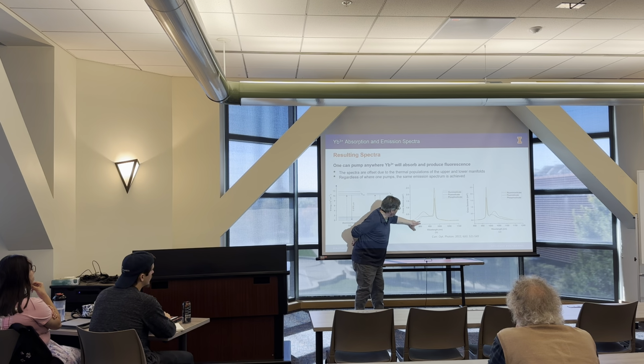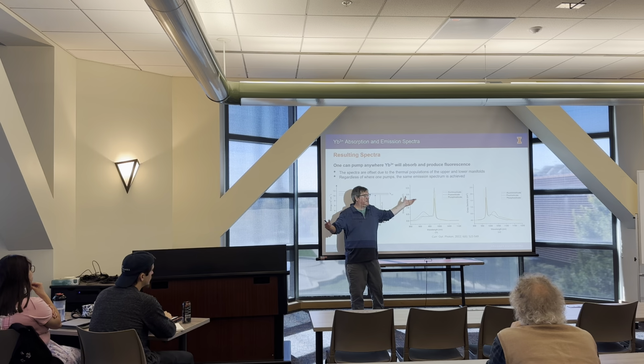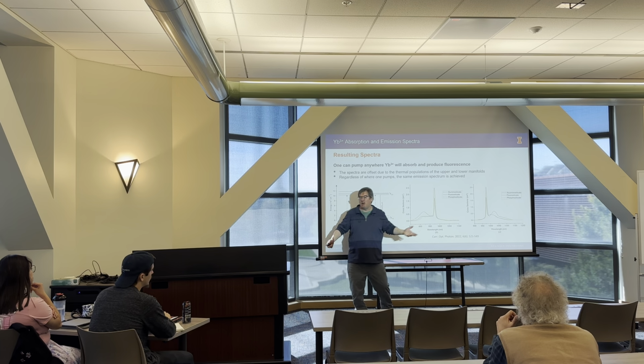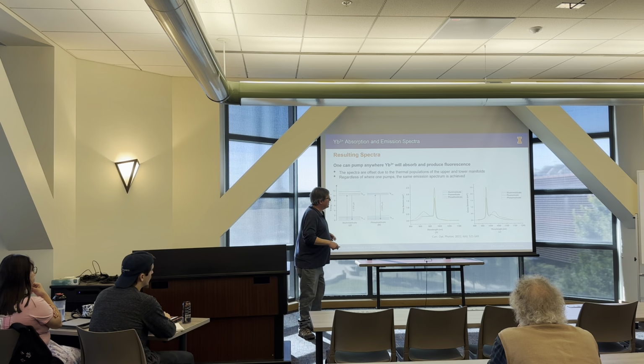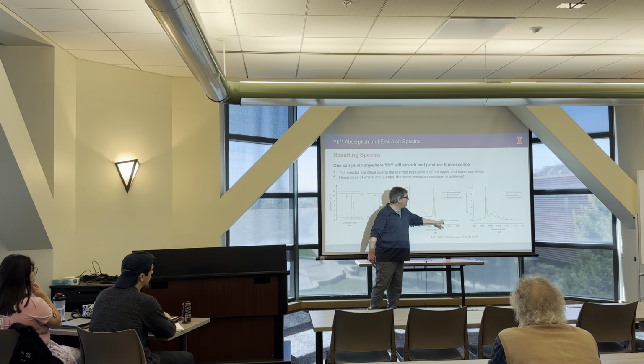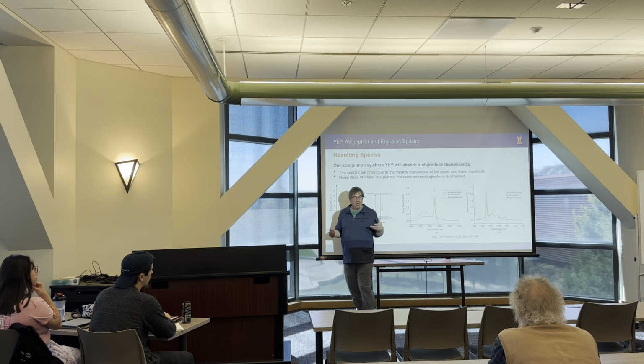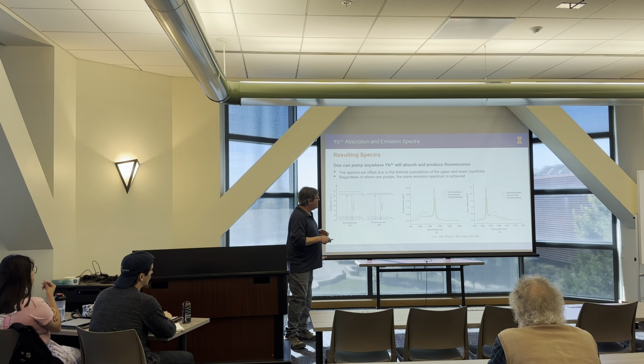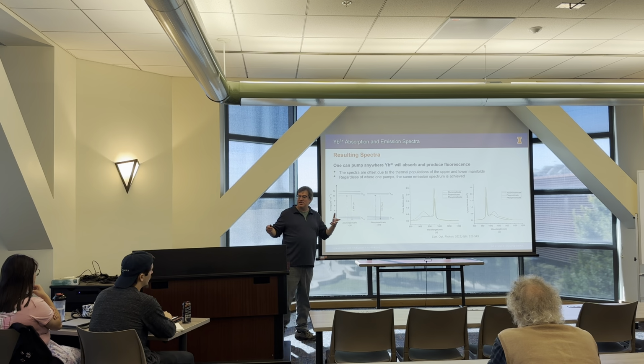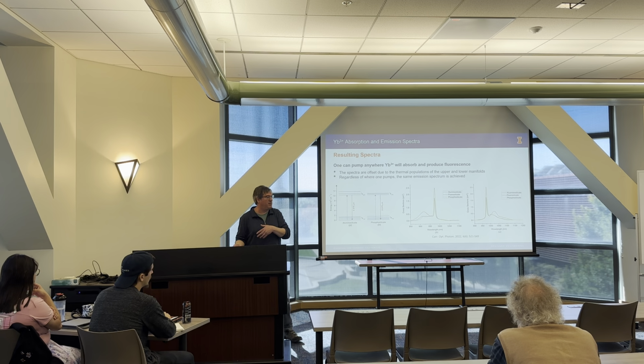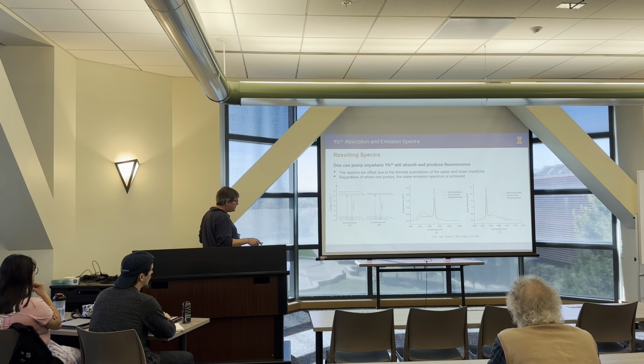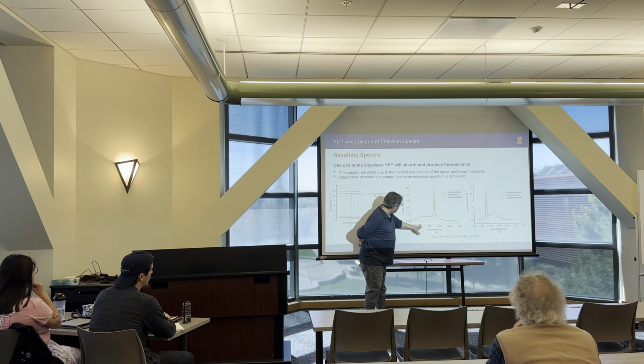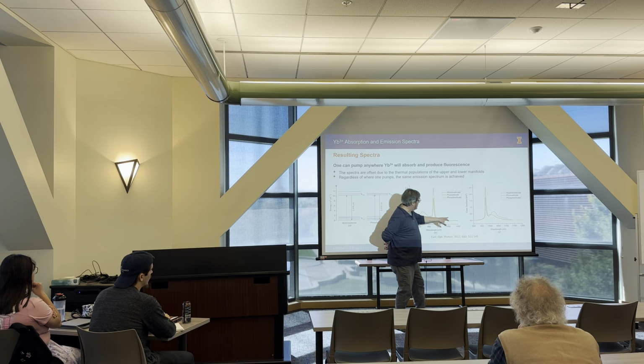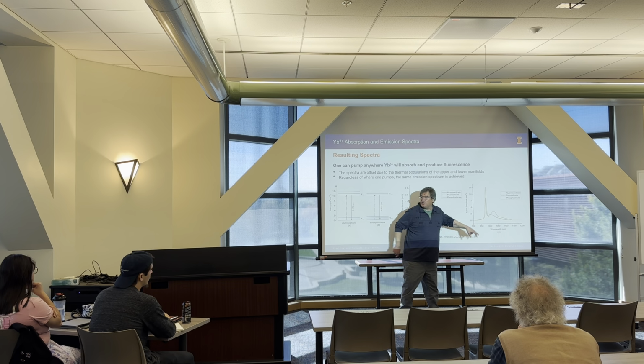If you look at this, you could pump anywhere where the absorption cross section is non-zero. It goes basically to zero, and we can absorb anywhere in here. So for instance, if we pump at 1025, that's over here someplace. You'll see the fluorescence spectrum, which is independent of the pumping wavelength. Again, anti-Stokes is possible. You get a significant amount of luminescence at an energy higher than where you're pumping. And if we're pumping at 900 nanometers, where there's no emission, there's no way that we can cool the system.